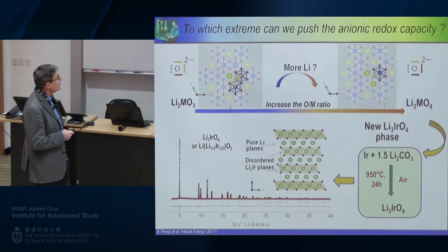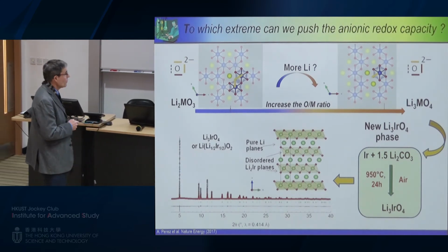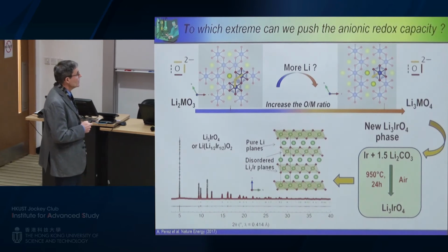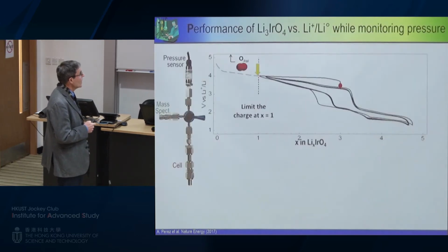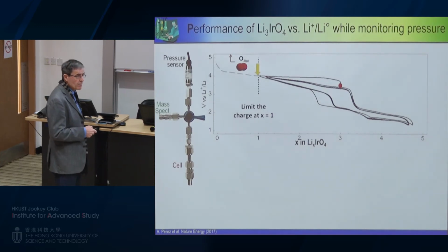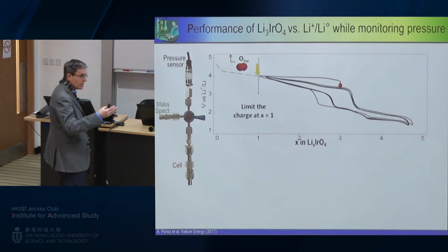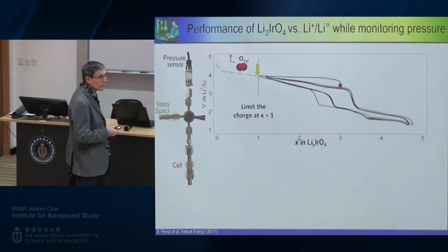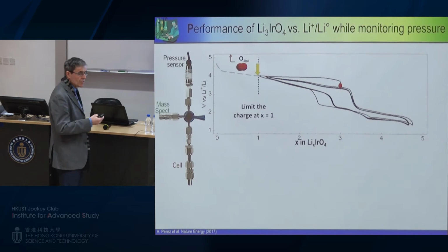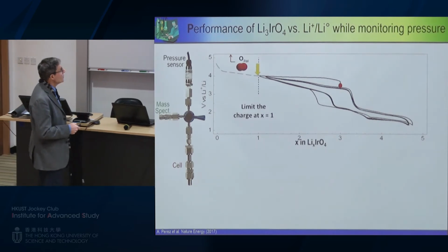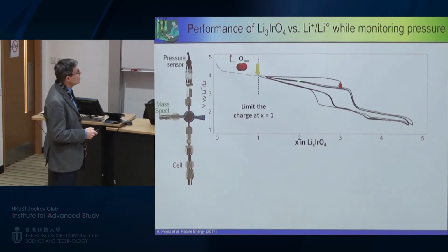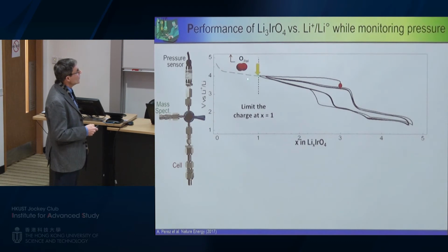And when we then look at the electrochemical properties of the material, as shown in the next slide, we measure the electrochemical properties using this type of cell, where at the same time we can not only count the number of lithium, but also measure the amount of oxygen that is released. And when we did the measurements, when we are charging, the red curve, we found that beyond x equal 1, we have nearly a release of oxygen.